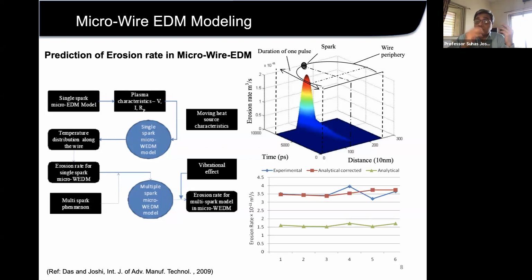And now we have also developed a software where you run the EDM process for a certain duration under certain parameters, and you get a certain surface. We also can run the software and get a certain theoretical surface, and we can compare these two surfaces, and we come fairly close by making certain assumptions, saying that this energy distribution will follow something, a spatial distribution of the sparks is something, and so on and so forth. But this was long ago, in 2009, about 10 years ago.